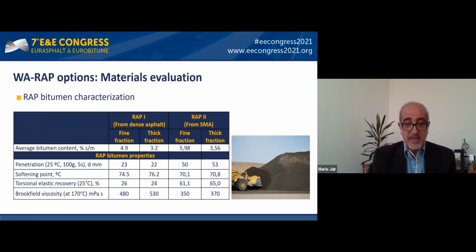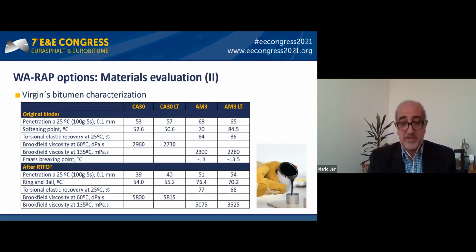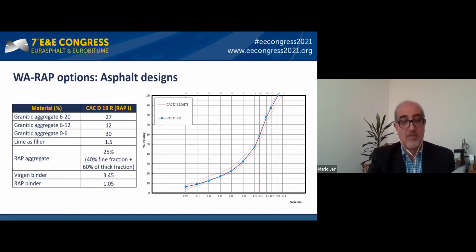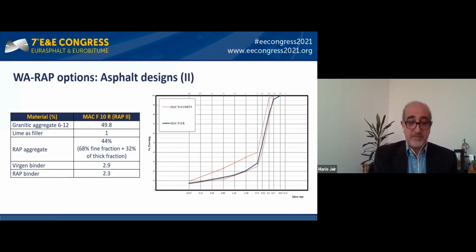Here you can see the bitumen characterization of the RAP, which was divided in 2 fractions. It is important to note the good elastic performance of the RAP binders, as they come from mixtures based on PMB. Continuing with the evaluation of materials, the characterization of virgin asphalt binders used for the test. The following are the gradation curves of the asphalt mix design. In this slide, for the asphalt option using 25% of RAP. And here is the curve for the thin asphalt with 44% of RAP.